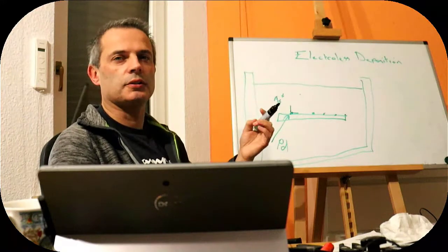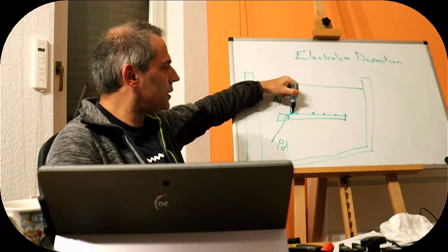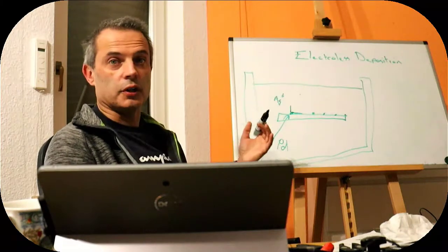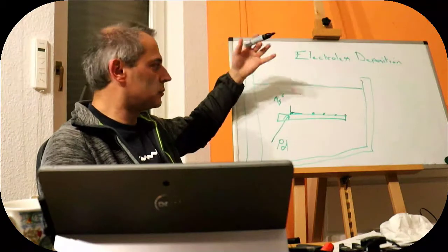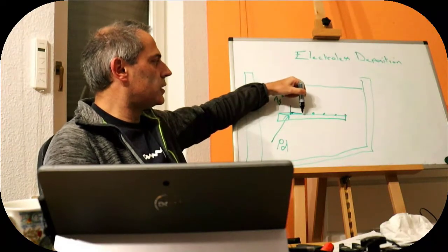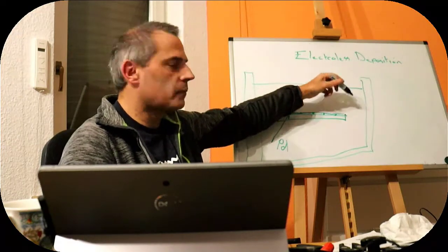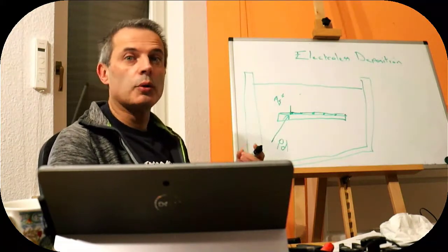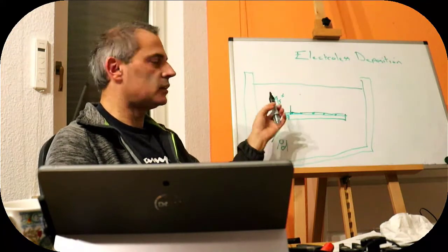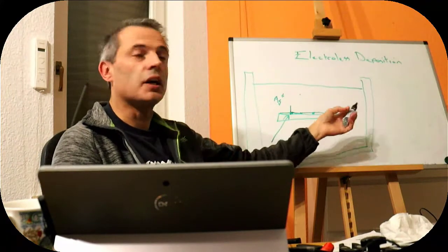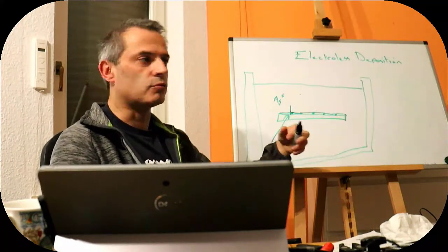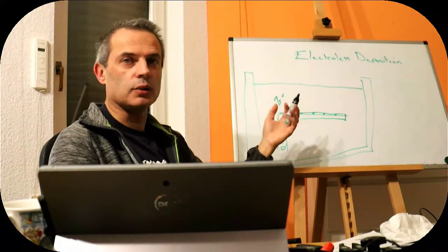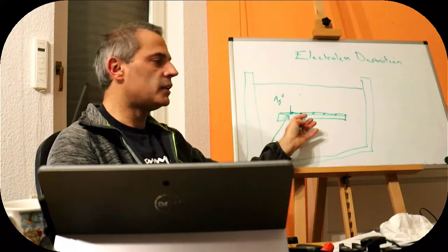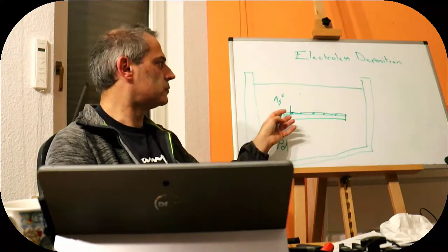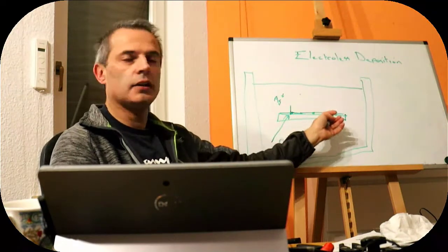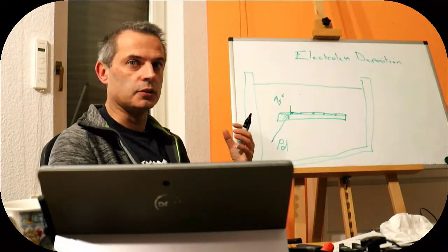We've just nudged it past its reduction potential, and so we're going to typically grow along the surface, and if we've got it right and we've got enough planarizing and other agents in there, we can generate a flat film on our surface eventually. That is what we would want to do. If we've got a polymer, we may have to treat it beforehand to make it stick to the metal and to make this process energetically favorable for it to grow along the surface rather than to grow out into solution or just make these particles really big. Obviously, a high surface energy of our substrate also helps to make the silver, in this case, stick to our substrate, which is good because that's what we're trying to do the whole time with this process.